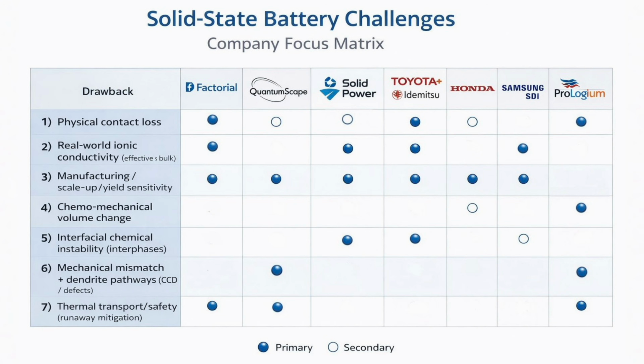Factorial Energy, for example, is going with those quasi-solid-state batteries we've already talked about, where the gel electrolyte will improve contact and conductivity, but more importantly, their quasi-solid-state battery is largely drop-in compatible. And even though gel electrolytes don't eliminate thermal runaway risk, they can improve safety and performance. QuantumScape is heavily investing in ceramic separator manufacturing for dendrite suppression and to raise the practical current limit and resist shorting pathways. Ceramic is also non-flammable, and the anode-free architecture that forms lithium metal during charging can address energy density, dendrites, and architectural change. Solid Power is using a soft solid electrolyte for ionic conductivity. Soft sulfides also have better contact than oxides.